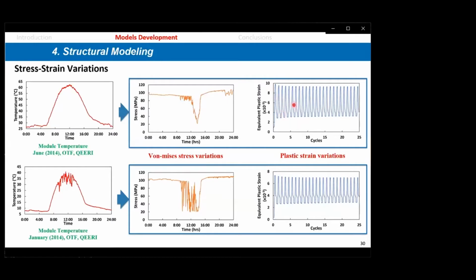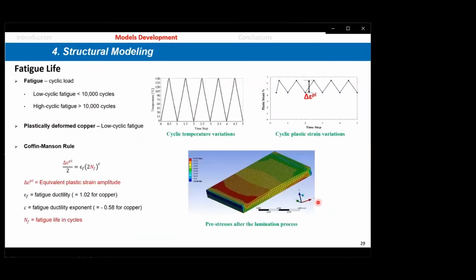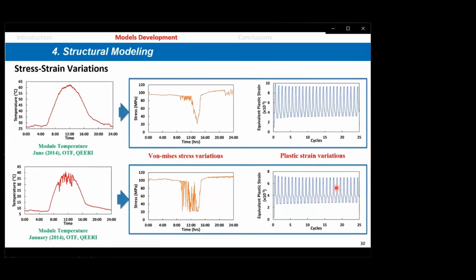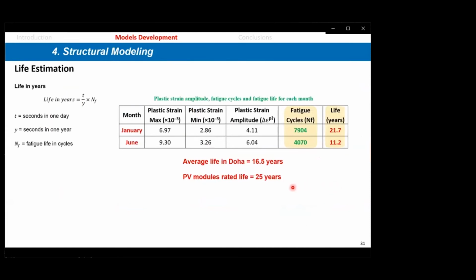As you can see, the amplitude of plastic strain stabilizes. It is a little bit higher in the beginning and stabilizes at 20 cycles, or 20 days. The same thing for the case of January: it stabilizes after 20 days or even a little bit before, and we use our model to predict the number of cycles. To use this model, we need to make sure that delta epsilon plastic stabilizes before we can use it. So it stabilizes at 20 cycles, and now we use this stabilized delta epsilon plastic, and we calculate the number of cycles, or number of days, that the panel will survive before the copper ribbon fails.